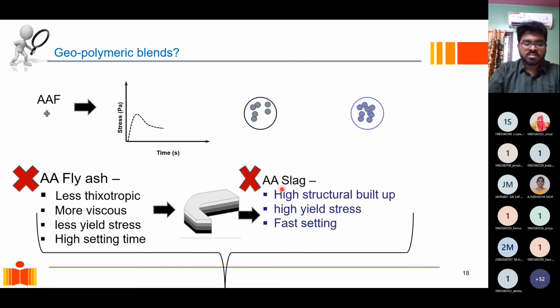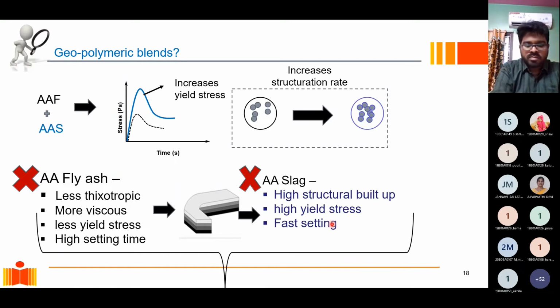Whereas when I only activate slag, I get a very high structural buildup, which is desirable. It has a high yield stress, which is desirable because then it will keep its shape when it's at rest. But it's very fast setting. It starts setting too fast, and then I have the problem of the material setting in the nozzle itself or while I'm pumping it. So therefore, we blend these two materials and create an optimal material, which basically gives us the best of both worlds. That's what we get when we blend fly ash and slag.